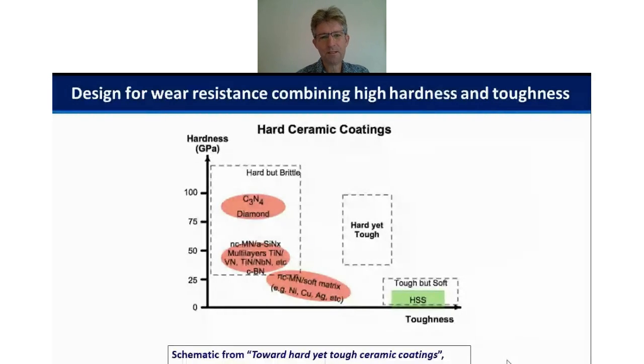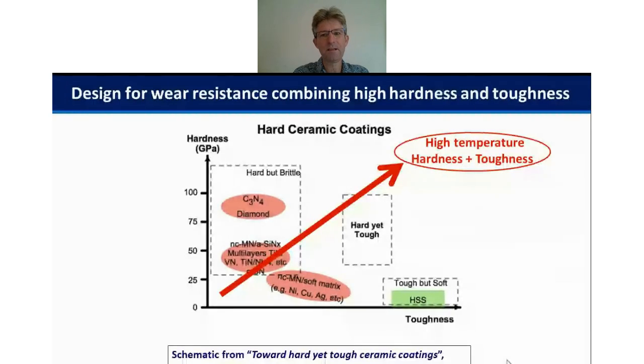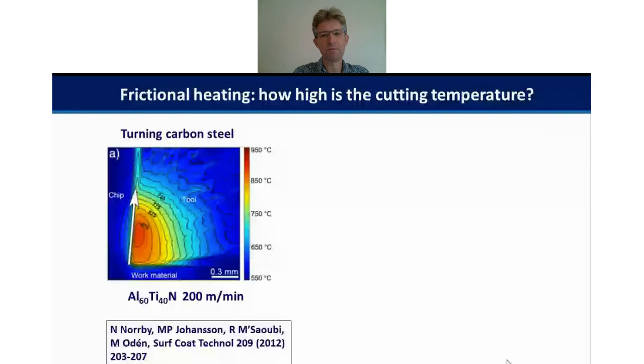So this is a schematic, as I said, and really, if you think of many of the applications of these hard ceramic coatings that Sam is thinking about, this is only part of the solution. Really what we need in these applications is a combination of high temperature hardness and high temperature toughness, and that achieves longer life of the coated systems. So a lot of our research revolves around evaluating materials for these extreme conditions.